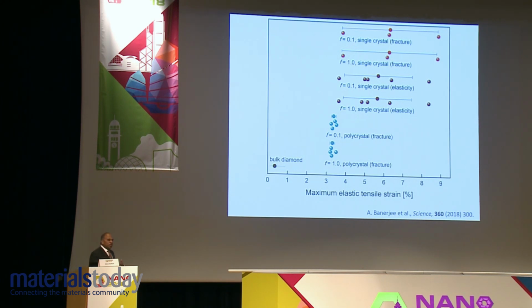So when you do a large number of these repeat experiments in single crystals, and I mentioned that there is a little bit of friction, in our computational simulations we tried to understand the effect of friction on the strength that we get. What is plotted here is maximum elastic tensile strain for single crystals under two different conditions. Elasticity refers to deformation without fracture, where we unload. What is the maximum strain we can get without fracturing? And in the case of specimens that fractured, what is the maximum tensile strain?